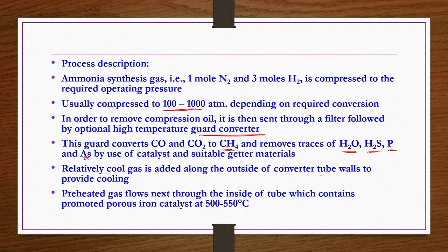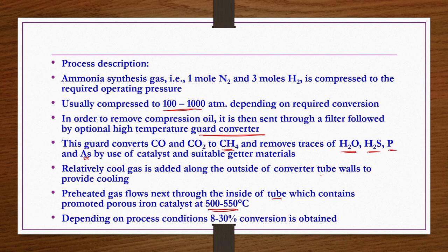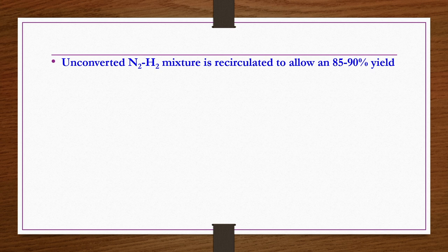Preheated gas flows next through the inside of the tube, which contains promoted porous iron catalyst at 500 to 550 degrees centigrade. Depending on process conditions, 8 to 30% conversion takes place in this process. Unconverted N2 and H2 mixture is recirculated to allow 85 to 90% yield. Otherwise, in one single run without recirculation, you can get only approximately 8 to 11% yield, 8 to 10% yield of ammonia only. So recirculation is one of the important parameters, to make sure the unreacted N2 and H2 are efficiently recirculated